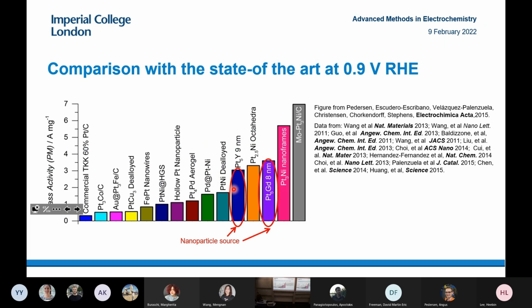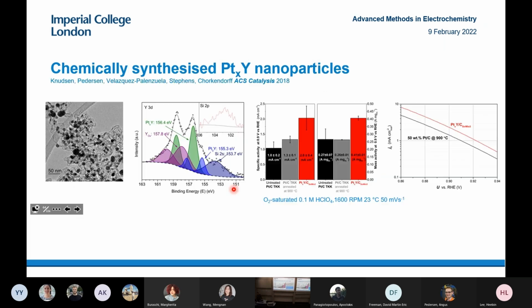So it showed it worked in nanoparticulate form, and it compared well with the state of the art at the time. Then we even found we could synthesize it chemically, but that was really a struggle. We had to get everything very clean of oxygen, but we eventually made it, and other groups have done it as well and also seen improvements. Key question, of course, is why did they actually work?